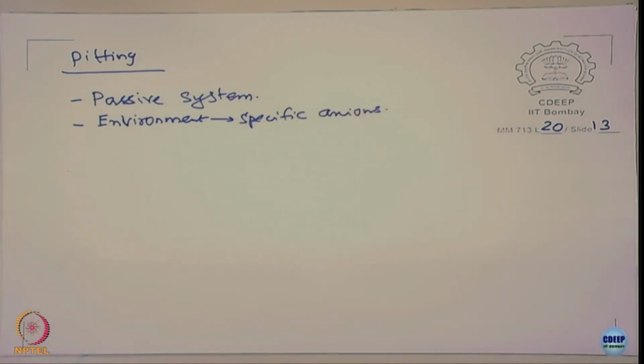I specially put it. Of course, cations also can influence, right. Can cations influence pitting corrosion? Yeah. Cation accumulation, of course, that is another part of it. I am talking about the environment. I am not talking about the cations dissolved in the pit and causing the pH change. I am talking about external addition of cations, if they are oxidizing agents. Yeah, oxidizing agents, right? Your ferric ions, cupric ions, mercury chloride, all the highly oxidizing environments can cause pitting. Environment, of course, but then anions are very important. Okay.